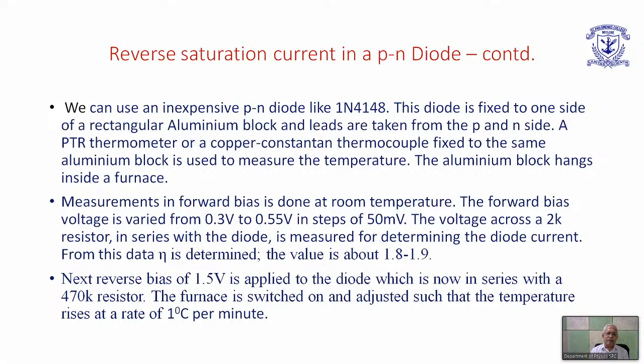In the case of the reverse bias experiment, we use a standard torch battery, 1.5 volt battery, and this is applied to the diode, and the diode is in series with a 470K resistor. Again, the voltage is measured across the 470K resistor to estimate the reverse saturation current, and the sample is placed inside a furnace because we have to keep raising the temperature. The furnace is designed so that we can increase the temperature at a very slow rate by properly adjusting the current in the furnace. The rate of temperature increase is maintained at around 1 degree per minute in the experiment.